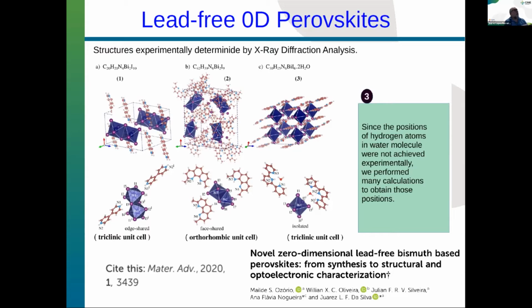And then what was done here? Those structures, you can see, are quite complex. It's a 0D structure in which one or two octahedrons are isolated, surrounded by organic cations, which balance the charge. In those organic cations, the bonds between the atoms are covalent bonds. There is a weak interaction, not covalent, but hydrogen bonds and a more Coulomb-like interaction, between the organic cations and the inorganic part, which in this case is not a framework but isolated octahedrons. But these structures are quite nice.